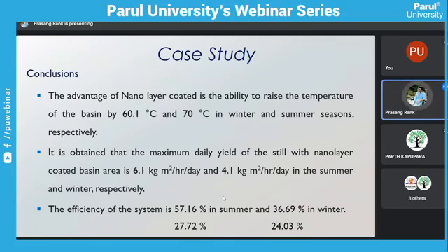Also, the efficiency of the system in summer with coating was 57.16% compared to the non-coating 27.72%. See how much the efficiency increased. And in winter season with coating it was 36.69% compared to non-coated 24.03%. So here we can see the differences. In summer, due to high heat, the efficiency increased 30%, and here we got only around 10 to 12 percent increase in winter. So if we use these modifications in different conventional plants, we can increase the productivity. The main aspect of these plants is to get more and more output with a lower operating and maintenance cost.